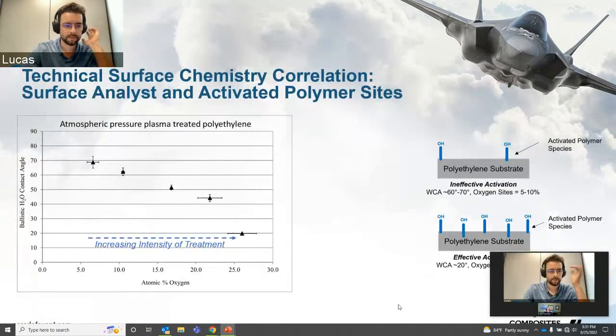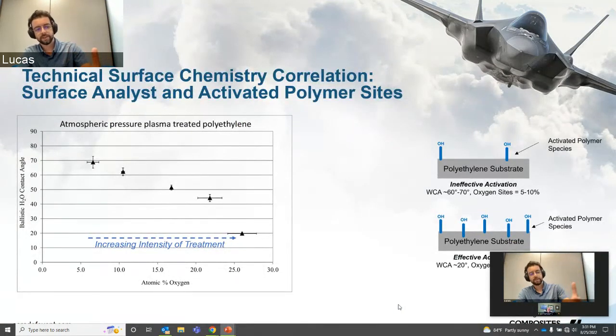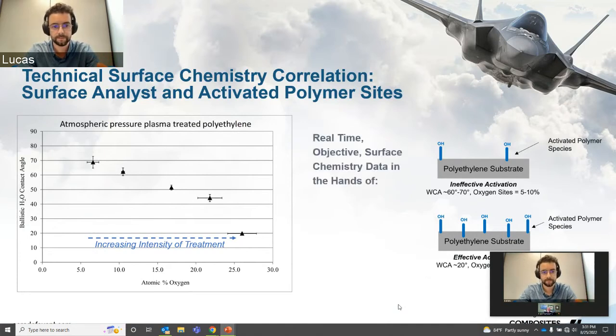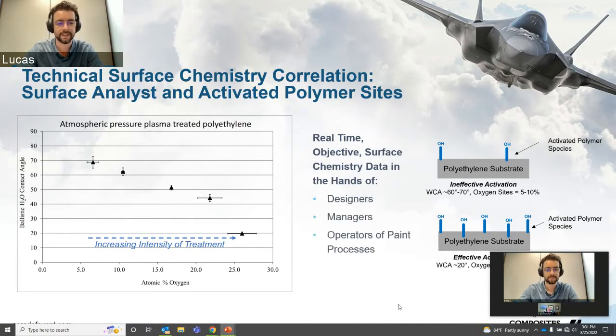You can go one forward, Ricky. Sorry. As you'll see in this slide, we can map our contact angle on the y-axis as a function of the atomic percent oxygen that we're putting onto this polyethylene through plasma treatment. Very similar curve shape, right? We get this in 2 seconds, and it's super sensitive and super accurate, and anybody can do it. So it's a very nice thing.